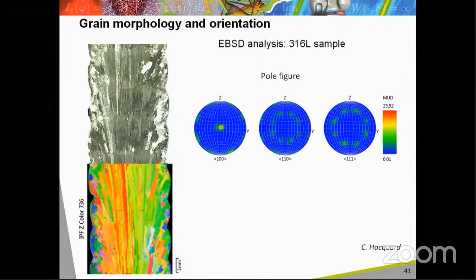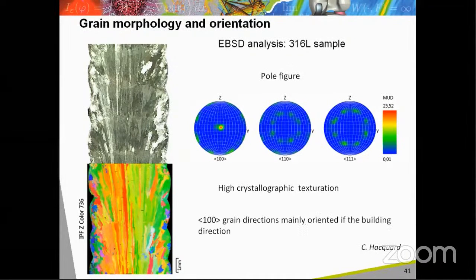The material has a crystallographic texture, as shown by the pole figure obtained from EBSD analysis of the material. One can see on this figure the 100 crystallographic axis of the grains is mainly oriented in the Z direction, corresponding to the build direction. This material's texture has a consequence on its mechanical behavior.